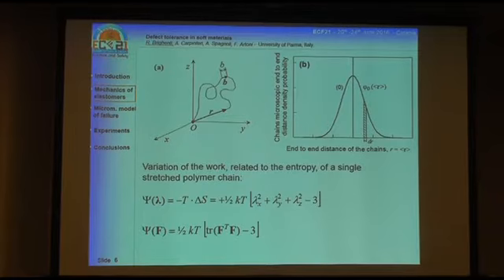We can easily calculate the mechanical energy related to the stretch of the material by simply multiplying the increment of the entropy by the absolute temperature. For example, if we consider simple stretching along the three directions x, y, and z, we have this expression here. And in general 3D elasticity, we have the mechanical energy psi, which is a function of the deformation tensor F by this simple expression, where we have the Boltzmann constant K here, the absolute temperature, and the trace of F^T F minus 3.